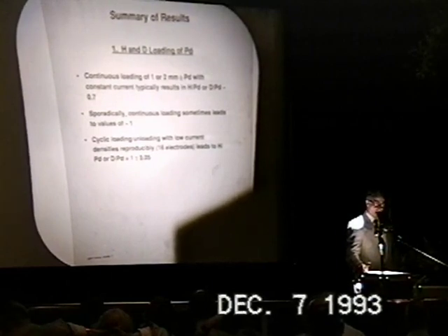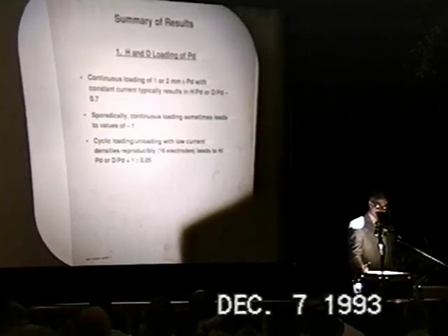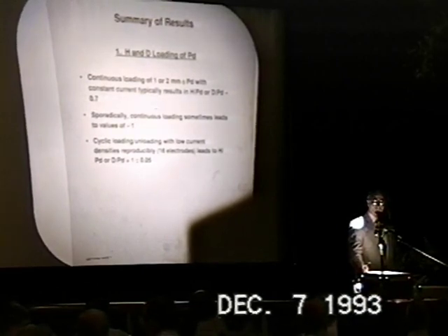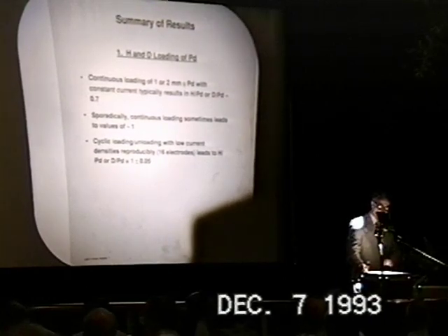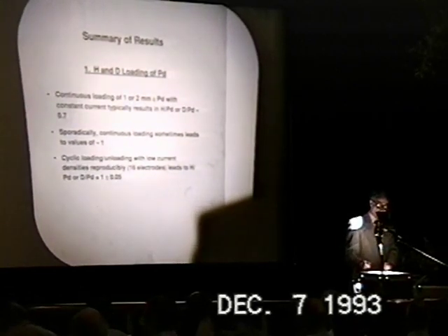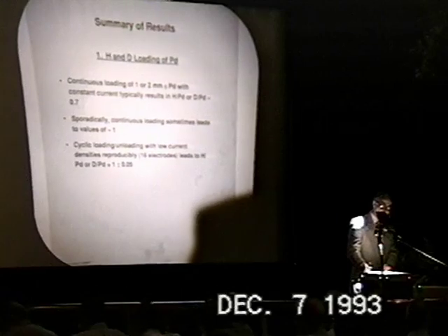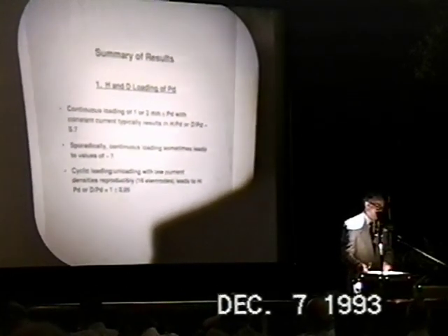In these 3 minutes, one can easily calculate with the known diffusion coefficients how much material could have been lost at maximum, and that loss could have amounted to about 5 to 7% of the hydrogen loading. So in most cases we started with gas-loaded loading factors already of 0.6 to 0.7 before electrolysis even started.